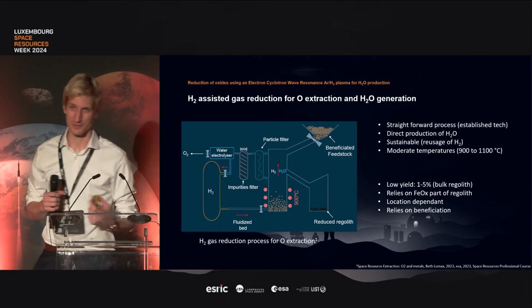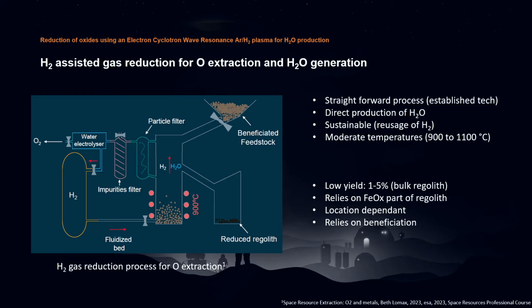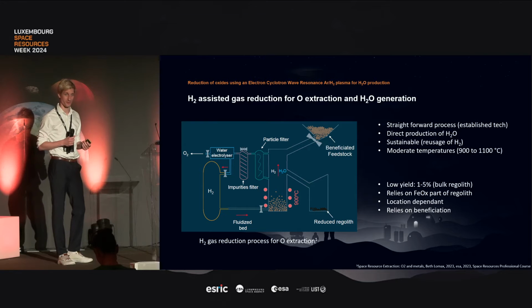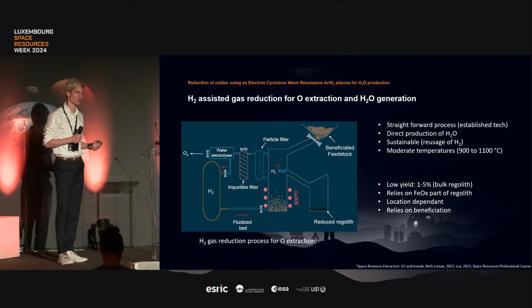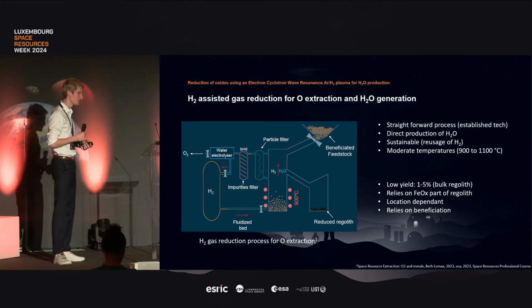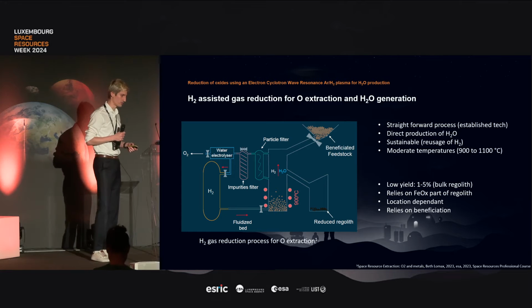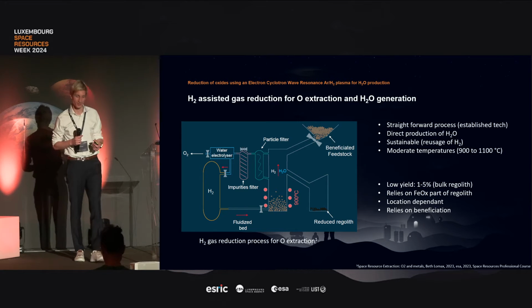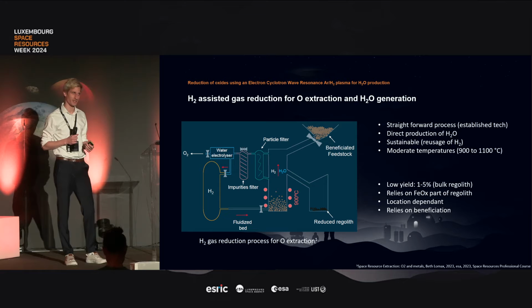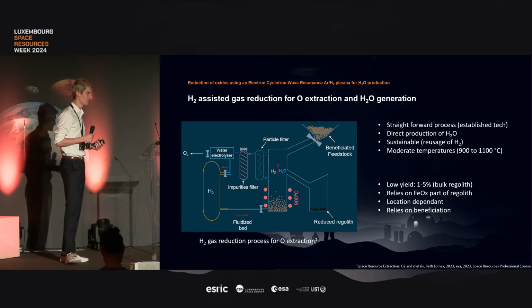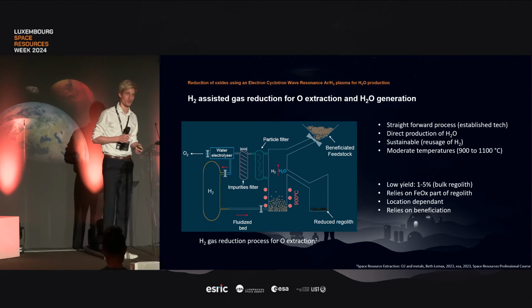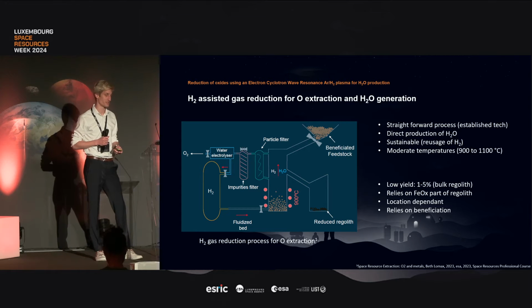So this slide you probably recognize from the professional course on the space resources. It demonstrates the hydrogen-assisted gas reduction process. The idea of that process is that we are directly producing water as we extract the oxygen, and it's a straightforward process, and it's also sustainable as we can reuse the hydrogen later as well. It uses moderate temperatures. It's not moderate enough to bake a pizza, but it's good enough for what we can handle with materials. The challenge of the process is that it has a low yield, and it will rely on iron oxides so that we are also location dependent and dependent on beneficiation.